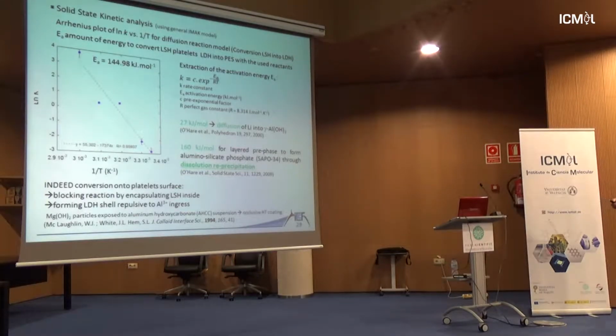kilojoules per mole. If you compare that to different layer structures, because of course you have to compare with the same dimension and the same type of materials: lithium into gibbsite, for instance, into aluminum trihydroxide, so just lithium diffusion into the vacancies, one third of the vacancies of the gibbsite, gives you an activation energy of 27 kilojoules per mole. So it's quite far from that. So probably it tells you that it's not diffusion.